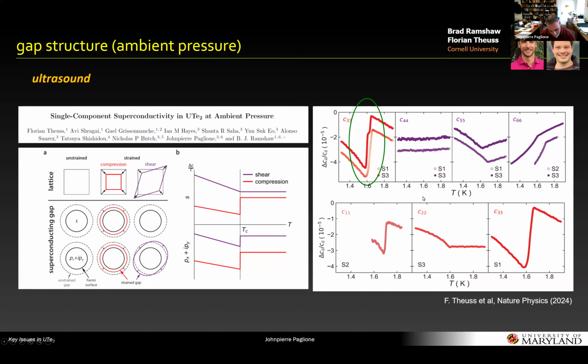And that's quite unusual. And I would say that leaves some room for interpretation, but nonetheless, why it doesn't respond at all is a good question. Now, one more note about that. If you look at Florian's paper, there's an added discussion about comparing the amplitudes of the compressive jumps in elastic constants. And there's an argument for a B2U order parameter, which would have nodes along the B axis direction, just based on the amplitudes of these. But there are other experiments, and I'll show a table at the end of the talk that compares all these things. So I think this needs to be put in context and understood more carefully.